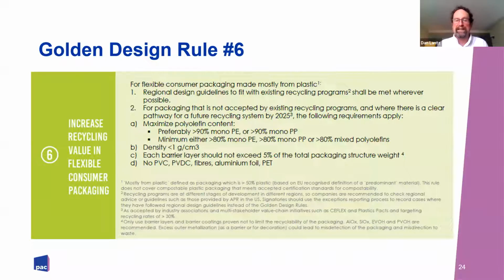Now, the second point is, if it's not acceptable, we need to look for a clear pathway for future recycling by 2025, and then the following requirements apply. Maximize the polyolefin content, preferably 90% mono PE. In other words, if you're going to have a multi-laminated pouch with a barrier layer in it, you would go PE barrier layer, but it has to be compatible with PE. There are examples of that in the marketplace today, and another PE layer. Preferably more than 90%. And in fact, preferably, talking to the end markets, more than 95%. And if you can get even less than 2% of other material, they're going to be really happy.